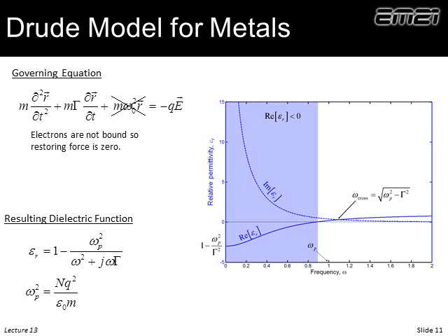Also recall the Drude model. It was the Lorentz oscillator model, but now the charges are not bound, they're free to move. We delete that restoring force term, and our equation differs a little bit. And what we see is below the plasma frequency, we have a very negative dielectric constant. The imaginary part goes through the roof, it's very lossy. Above the plasma frequency, it's essentially transparent. It's not a real sharp cutoff, but we train ourselves to think this way, that above the plasma frequency, metals are transparent. Below that, it's acting like a metal. But as you can see, it's not a sharp cutoff.